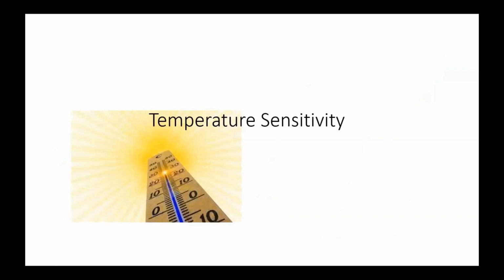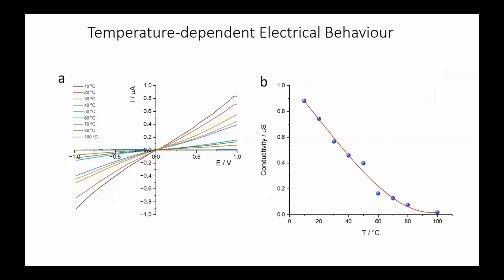What I mean by multi-stimuli and multi-response, we start with the temperature. When we apply a range of temperature from 0 to 100 degrees, we can see that the conductivity of the latex is degraded until around 100 degrees Celsius, where we do not have any electrical response. This was done when we apply 1 volt.